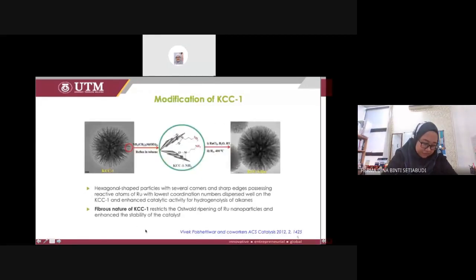Okay, then because of those superior properties, Vivek Polshettiwar and co-workers have done many modifications. Some of them as reported in ACS Catalysis in 2012. This is about the ruthenium species dispersed on the surface of the KCC1. When they did the modification, they found that the hexagonal shaped particles, this one, with several corners and sharp edges, possessing reactive atoms of ruthenium, this ruthenium, with lowest coordination numbers, disperse well on the KCC1. Because of the shape of the ruthenium and the dispersion of the ruthenium, the whole catalyst can enhance the catalytic activity on the subsequent reaction.